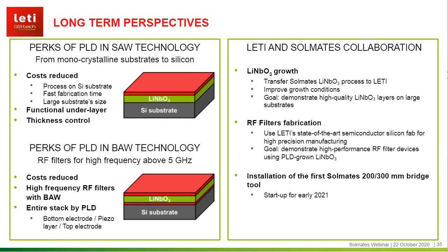From our point of view, PLD seems to have a bright future for radiofrequency device applications. For SAW technology, it will help reduce the production cost by enabling a process on silicon substrates, but also reduce the production time and maybe even be developed for large substrate sizes. Moreover, underlayers could be used under the piezoelectric layer. And finally, the thickness of the piezo layer can be controlled, which is also an interesting feature for both technologies.